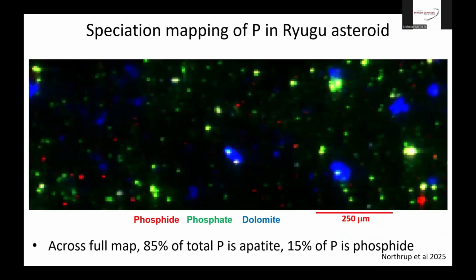So I'll give an example of that. Again, back to the Ryugu asteroid. Although I had said before that the phosphate spots were all apatite, well, it turns out that not all of the phosphorus spots in the sample are phosphate. Some are phosphides. So we can actually map the distribution of phosphide and phosphate within an area of the sample by mapping it at two energies and then doing the math. So this map shows the bright green spots are the phosphate spots, and the fewer but definitely there spots of red are phosphide, and that's an iron, nickel, chromium phosphide, which is a very interesting compound that's not found on Earth, but it is found in this asteroid.